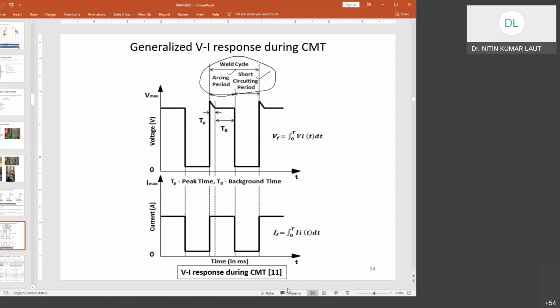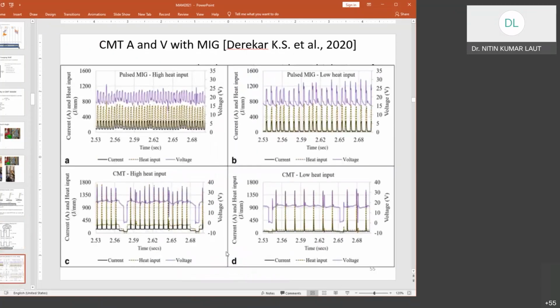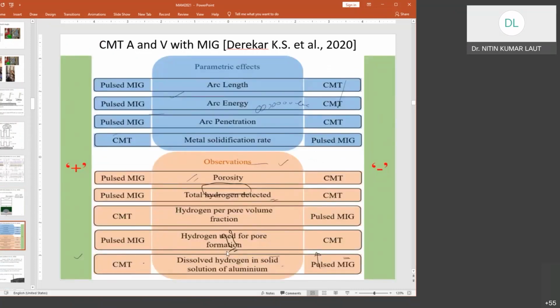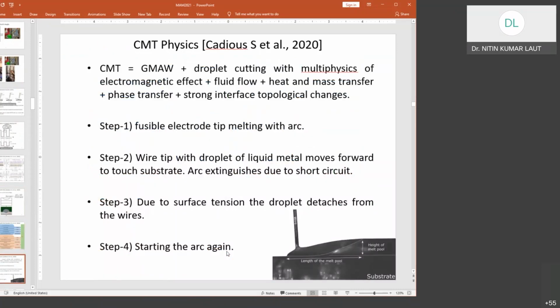But the interesting thing which you'll find here in CMT is that most of the time the current is kept well stabilized compared to the voltage. And in an earlier slide we have seen that the arc length is affected by voltage. So the process is also playing with the voltage waveform rather than the current waveform. So most of the time we'll see a stabilized waveform as far as current is concerned. I have other case studies also.